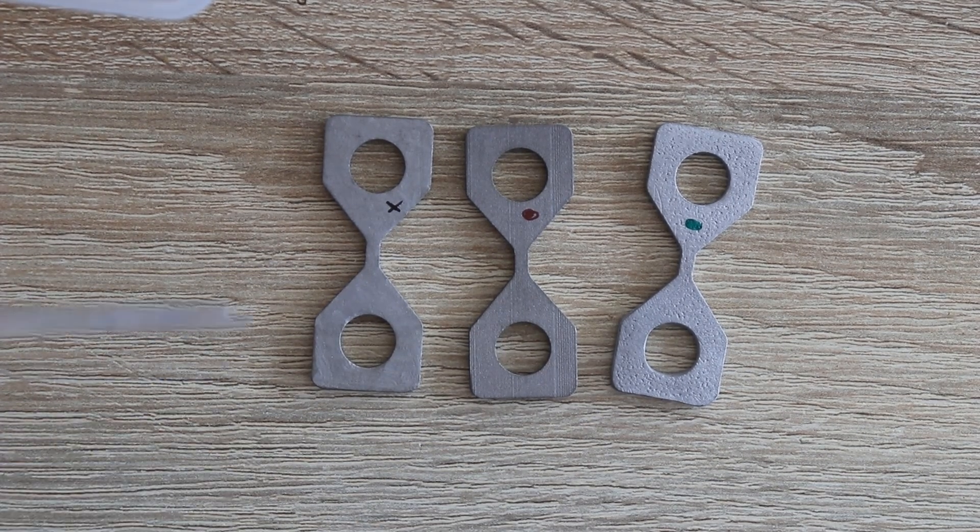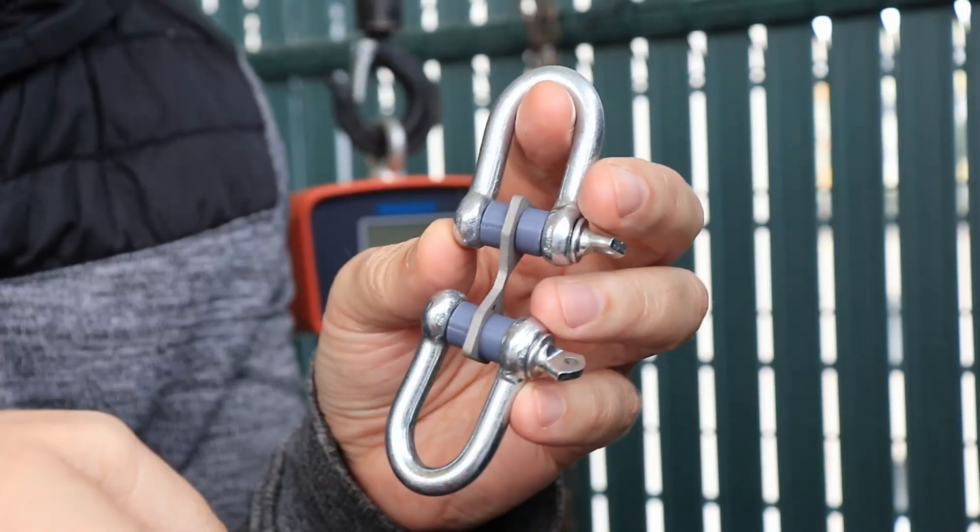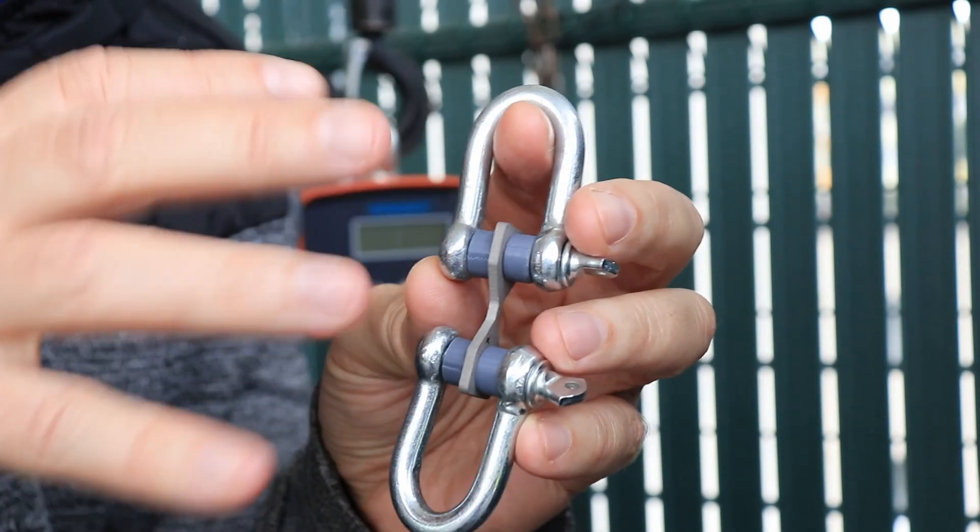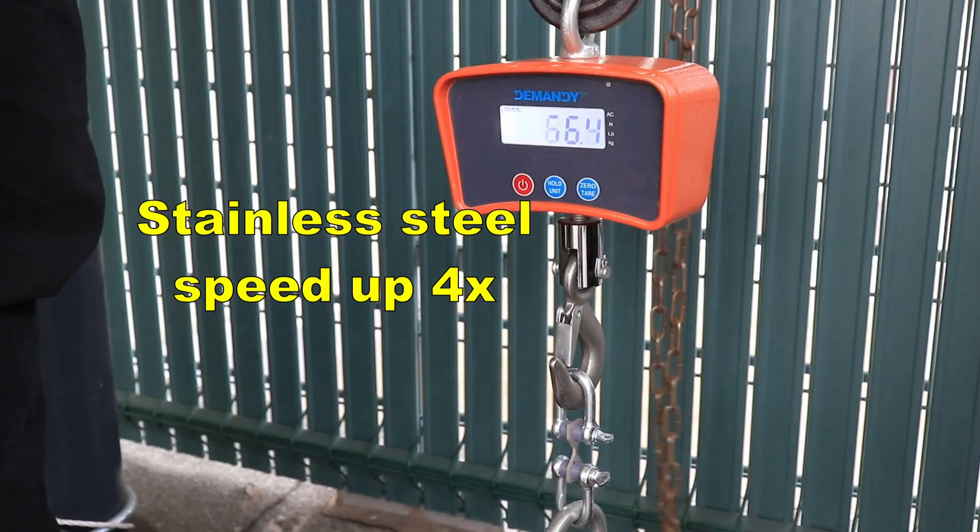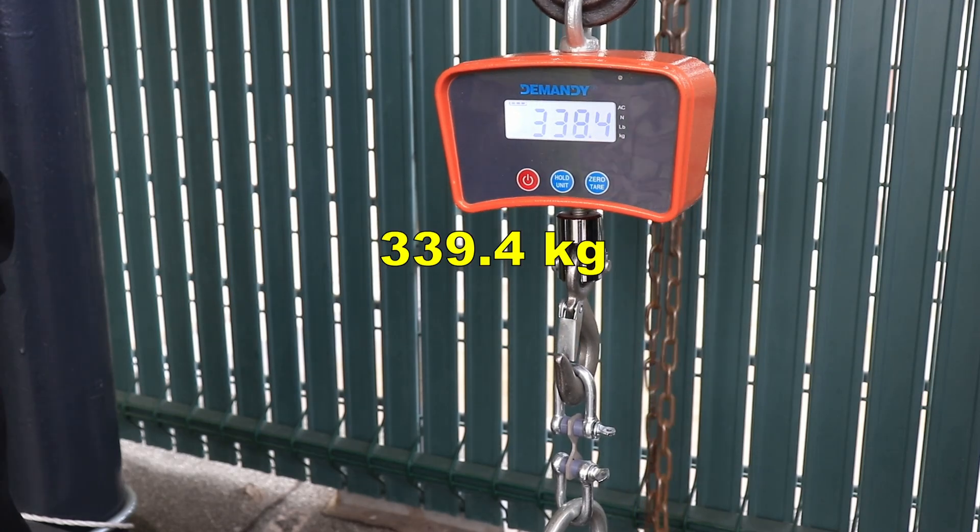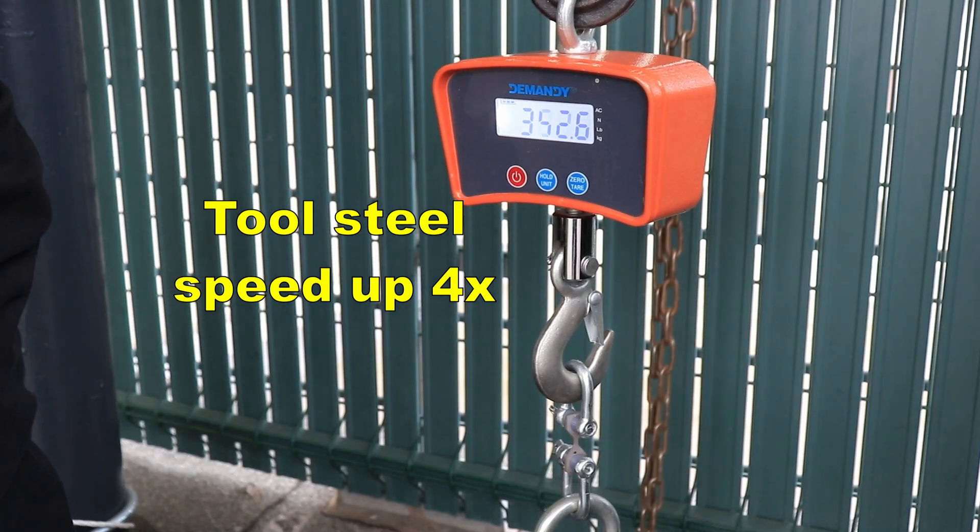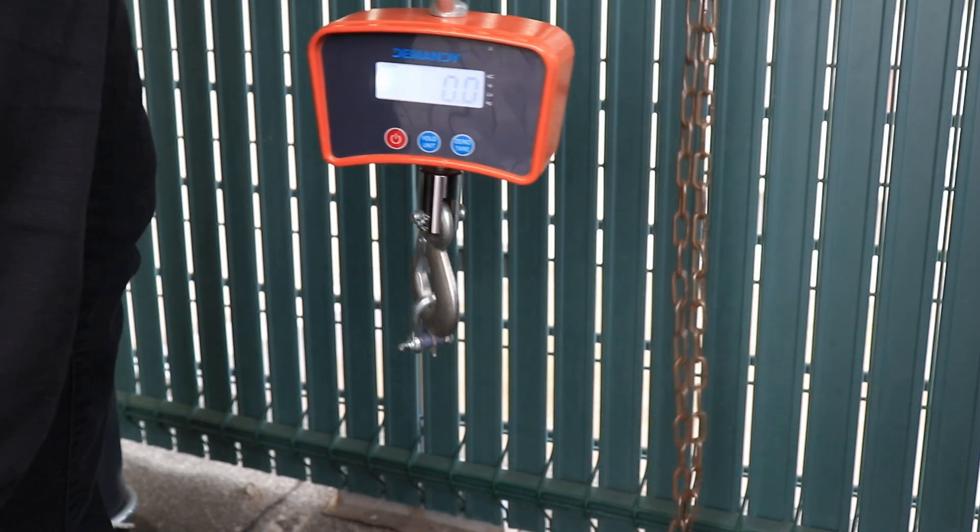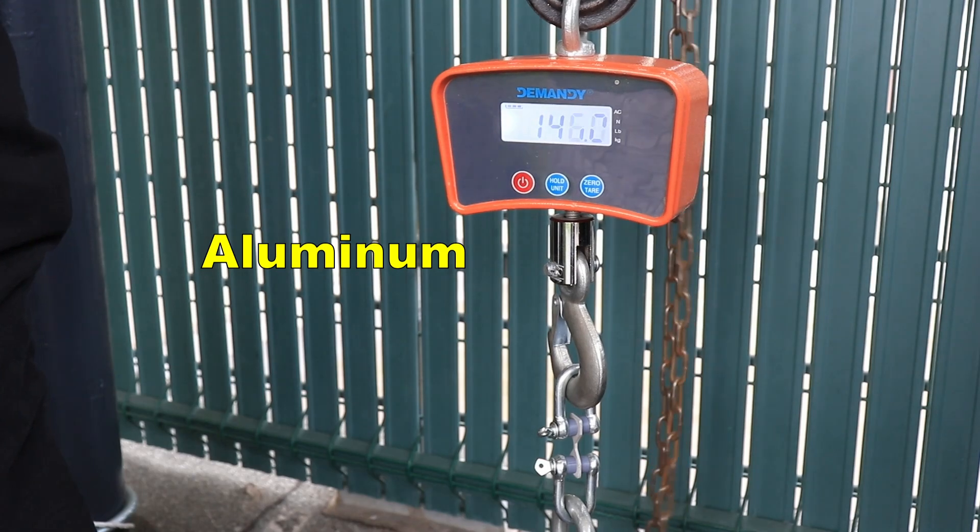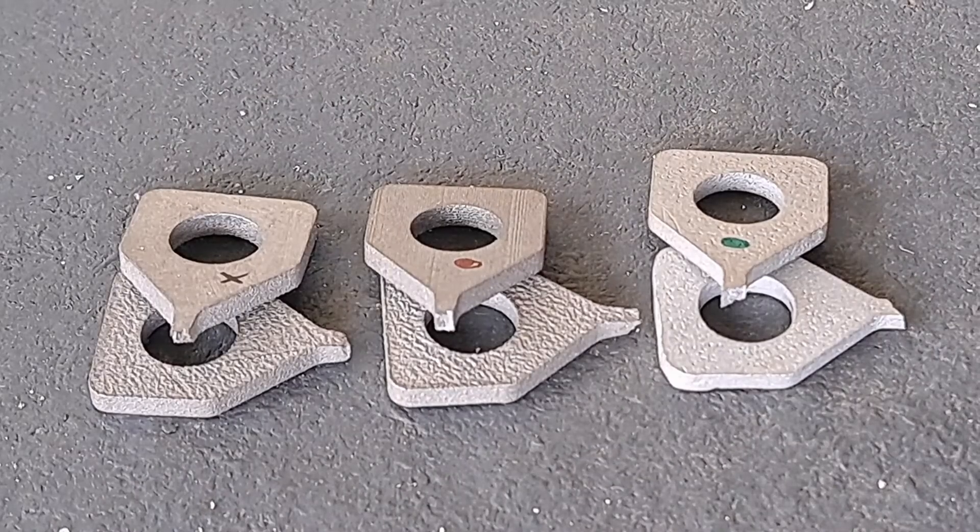And I am starting with tensile pulling test. These test objects are printed in horizontal position. And the smallest cross-section area is 2x2 mm, but I measured approximately they are actually 2x2.2 mm in all three cases. And just for comparison, same size regular PLA would break between 20 and 25 kg approximately.